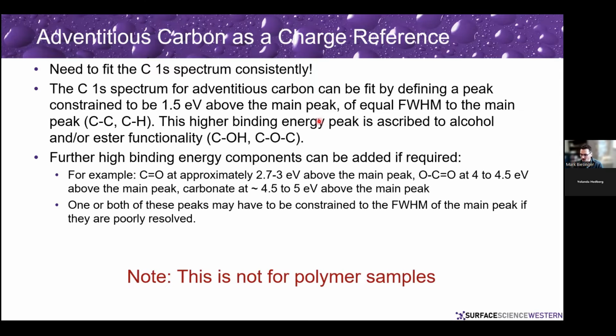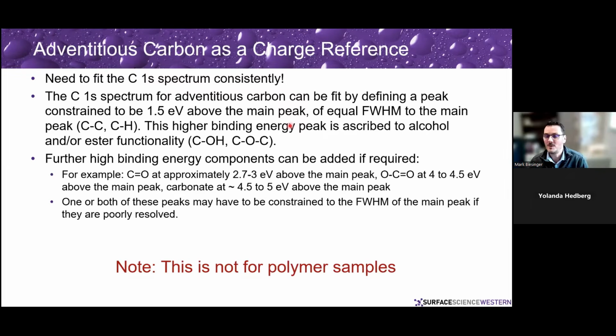Note that this is not for polymeric samples. If you have a polymer on your surface or you put some organic material on the surface, that's no longer adventitious carbon that you're fitting. But the aliphatic peak of those polymers, if it's there, or of that organic material, if it's there, and it may not be there, like if you have ring structures or lots of double bonds or lots of other things, you may not have aliphatic carbon in that spectrum. And so you cannot charge correct to an aliphatic peak in that spectrum if you do not have it there. But if you have it there and you know what it is, you can fit that, and that aliphatic peak should be at 284.8 type of spacing.